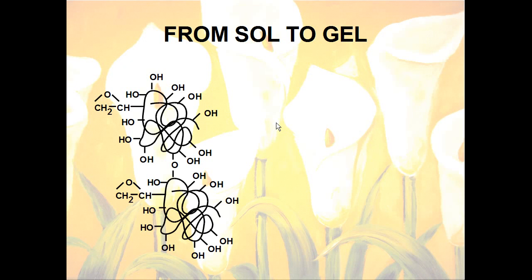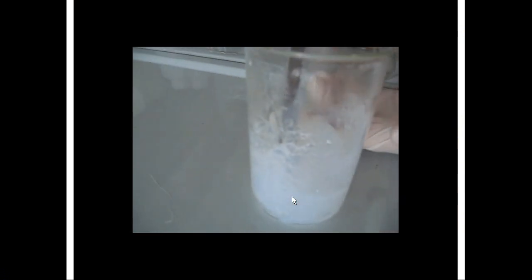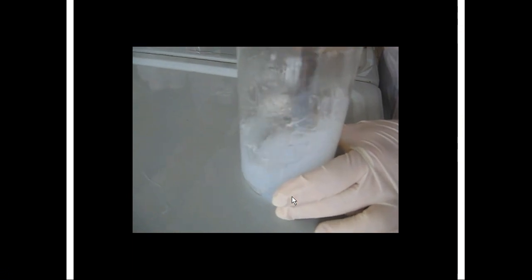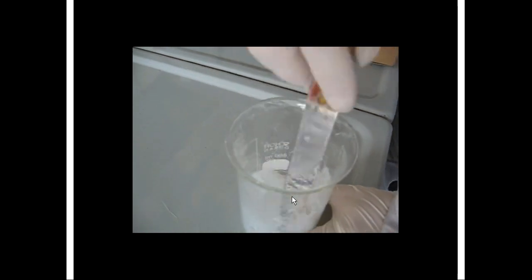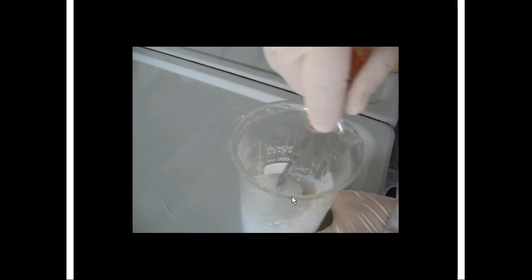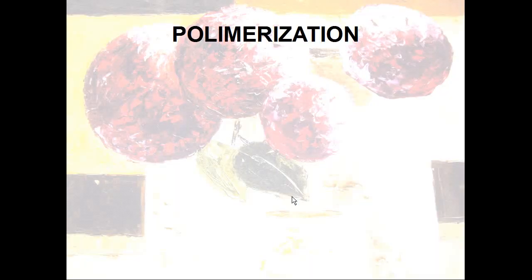But our prepolymer is only the beginning. Particles of prepolymer can bond together, and in this way the polymer can grow up. In this case, if the polymer grows up, the appearance changes. It becomes a little bit whiter because the size of the particles now begins to interfere with light. But mainly it becomes more viscous because we increase the degree of polymerization, and the polymer still remains soluble.